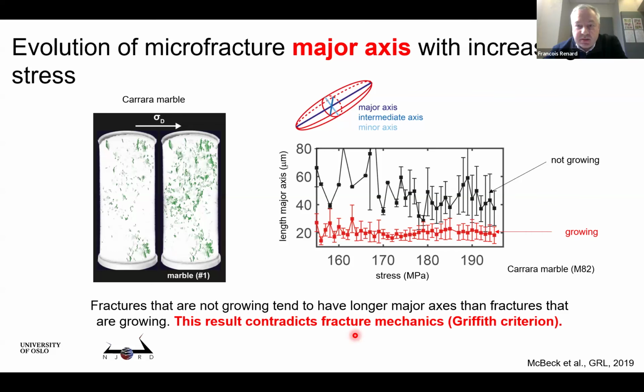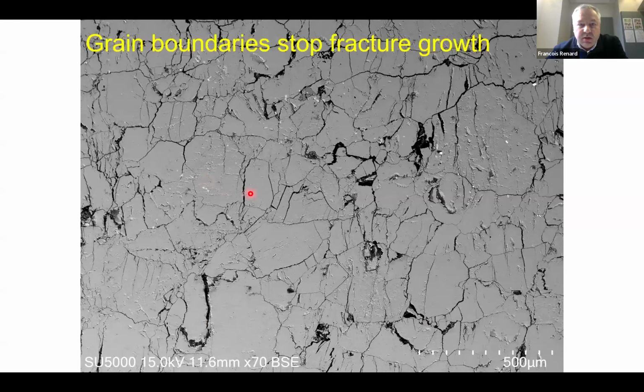Does it make sense? And the answer, in this case, is yes, because of the rock. It's a Carrara marble. We took this sample after the experiment, sliced it and made a thin section. And that's what the sample looked like. So it's quite damaged. All the black is porosity, cracks. But for example, here, that's a grain, a Carrara marble grain, and that's a fracture.